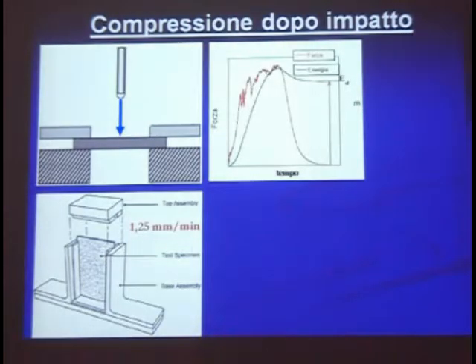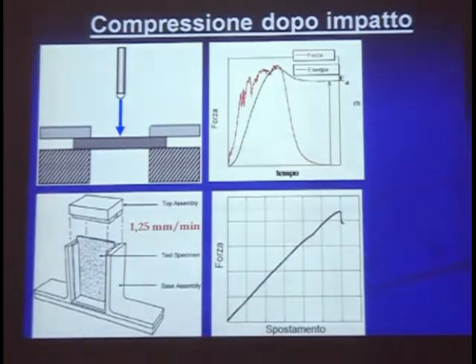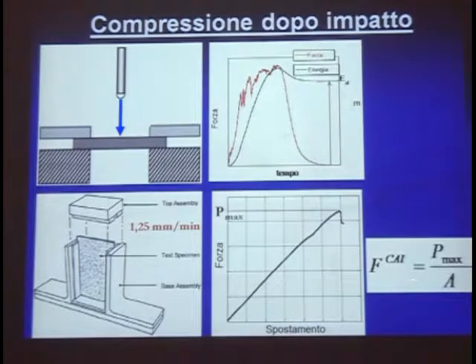And then we have been going through a compression test. This is a standard picture for composites. It has two rails in order to stabilize the specimen, and then the top assembly is used to put the compression load on it. And this is the typical load displacement curve, and one takes the maximum force divided by the area and gets the stress, the strength of the material after impact.